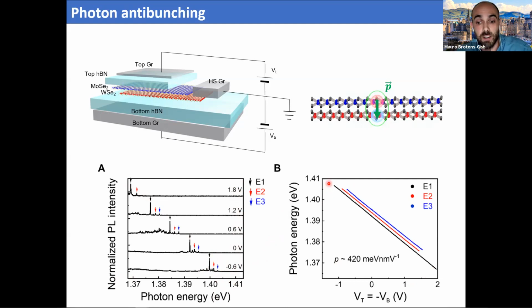Again, this is very exciting for us because we've been working in our group for quite a long time now with 2-dimensional quantum dots, and these are the first quantum dots whose energy we can tune, let's say, efficiently, right? And this means that for the first time, we are now in a good position to try to tune these quantum dots in resonance to cavities, for example, which we haven't been able to do because before we were relying on the fact that when you were exfoliating the material, you were lucky enough to get a quantum dot with the wavelength or the emission energy that you wanted, right?